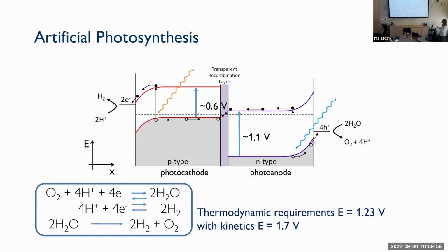So here I'm just highlighting that the right choice of materials should have at least one of them at over 1 volt, and the other one at around 0.6 volt. And I'm not choosing this 0.6 volt by chance, it's silicon. If you shine light on silicon, you usually get at least 0.6 volts. So we can start from silicon and then try to find a material that can match silicon, and then we can split water on top.